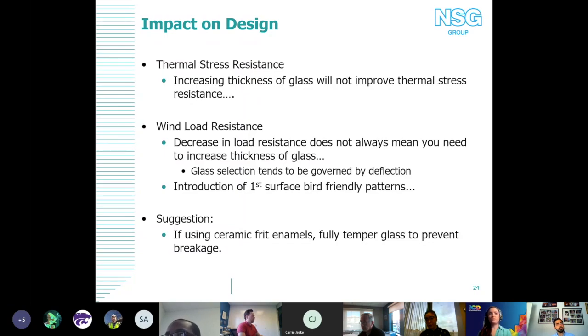Impact when you're designing for wind load. Well, by adding a percent reduction, it doesn't necessarily mean that you're going to increase the thickness of the glass. A lot of times you could add a 20%, 30% strength reduction, and it's not going to change what thickness you're selecting, because most of the time when you're designing for wind load, the glass selection tends to be governed by deflection and not by load resistance. So most of the time you won't even see a change with regard to your wind load resistance.